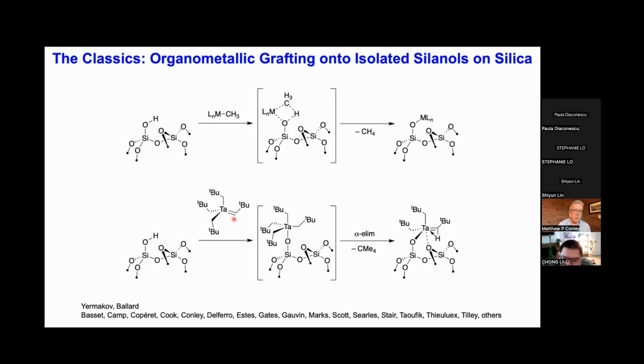organometallics that contain metal carbon multiple bonds, and this is a classic example using Schrock's tris-neopentyl neopentylidene tantalum in elegant work by Basset. He showed that if you selectively label the silica to contain deuterated silanols, react it with the tantalum alkylidene, there's evidence for formation of this tetraalkyl site where the proton has been transferred to the tantalum carbon multiple bond, which is then followed by alpha elimination to generate your well-defined product.